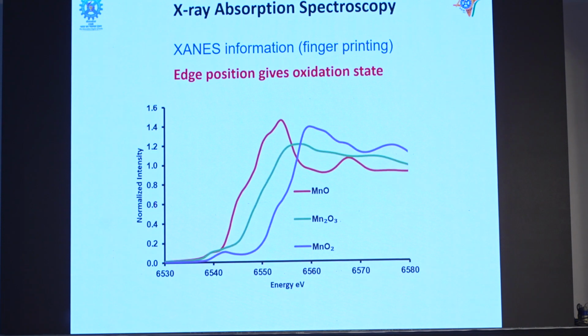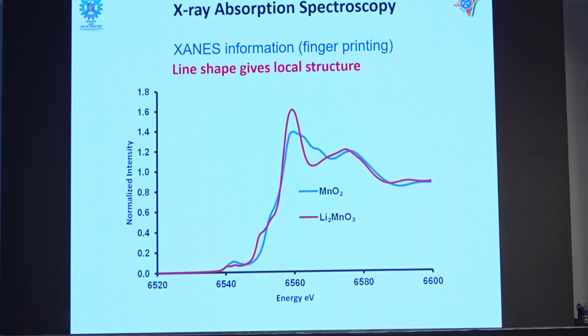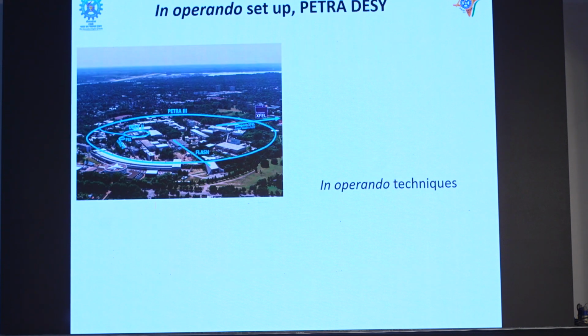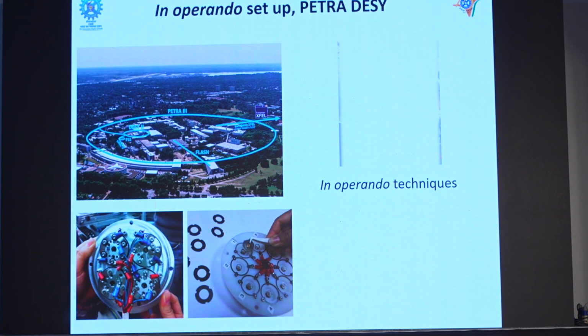So here we can see the oxidation state is different, and we have a different position for the lines. And here the oxidation state is same, but the crystal structure is different, or the coordination environment is different. We end up in different line shapes. And we are doing it in a setup like this.